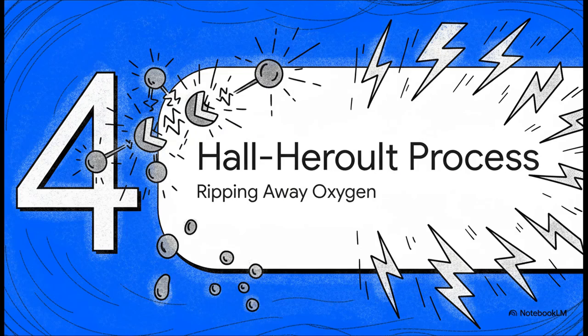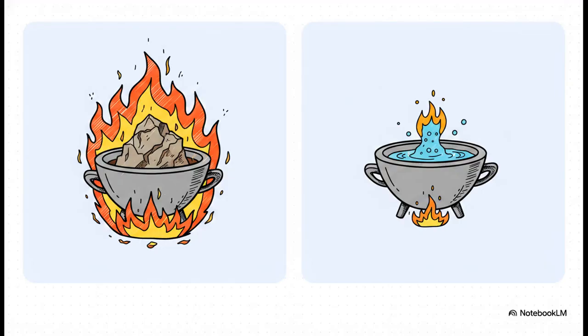All right, part 4, the Hall-Héroult process. This is where we finally rip away the oxygen. So right out of the gate, engineers hit a massive wall here. Pure aluminum oxide has a normal melting point of around 2273 Kelvin. Trying to reach and maintain that kind of crazy heat on an industrial scale is just devastatingly difficult and expensive. Melting pure alumina was practically impossible for a commercial operation.